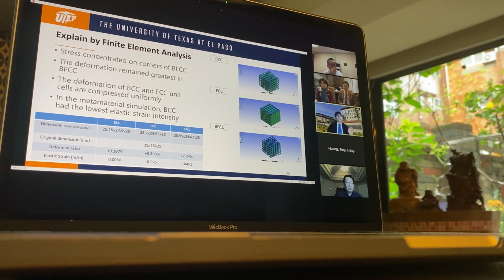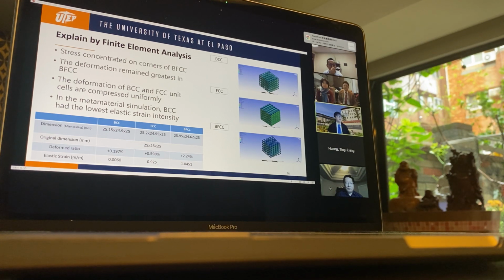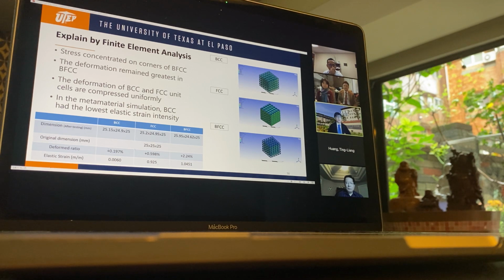So in the end, the simulation results showed us most deformation happens in the BFCC, which increased about 2.24% of the deformation. And the BCC and the FCC collapsed uniformly, not like how we anticipated. We'll follow the 110 or 111 plane. So we observe the lowest elastic strain intensity in the BCC, which is reasonable to account for the shape recovery speed, because the shape is uniformly deformed, and that can very efficiently spread out the energy into the deformation and recover it.